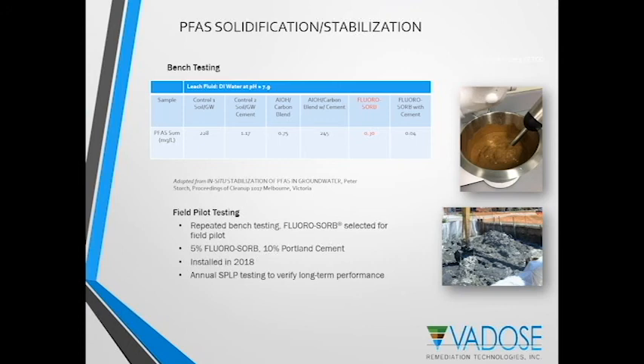So this work was done more recently. The same bench testing was repeated by Arcadis, and then Fluoro-Sorb was selected for a field pilot. It was installed in 2018 with 5% Fluoro-Sorb and 10% Portland cement as the mix design, and then annual SPLP sampling and SPLP testing will be conducted to verify long-term performance. However, it takes time for that data to become available, and so far it's not.